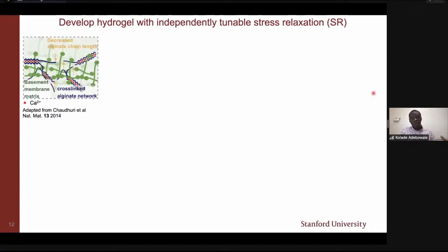So in this part of the project, we utilize hydrogels with independently tunable stress relaxation properties. These hydrogels consist of 2 main components. The first is basement membrane matrix or matrigel, shown by the green lines, which the cells can actually bind to. And the second component is alginate, shown by the dark blue lines. This alginate is ionically cross-linked by adding calcium ions. The way that we can modulate the stress relaxation behavior is simply by changing the molecular weight of the alginates.